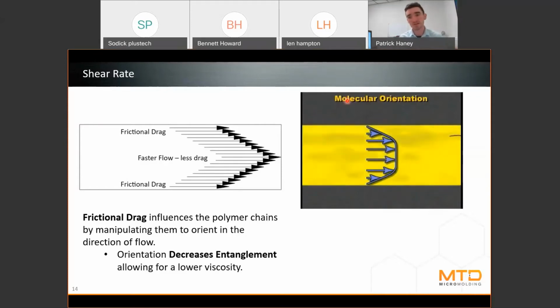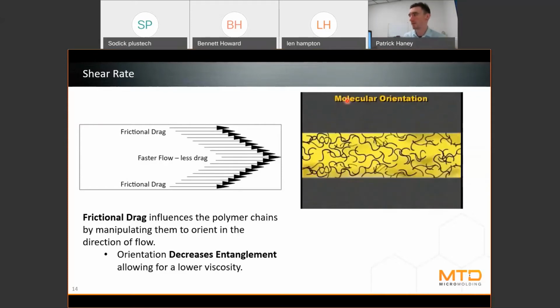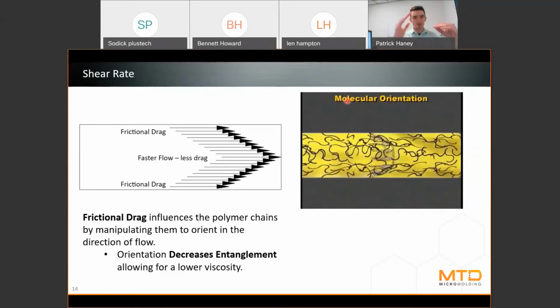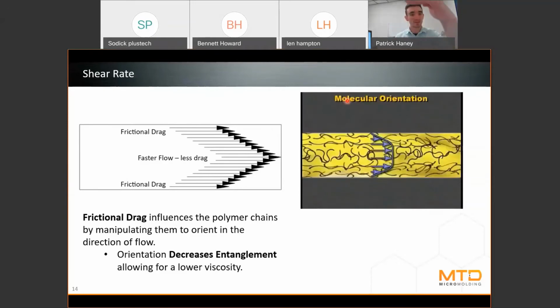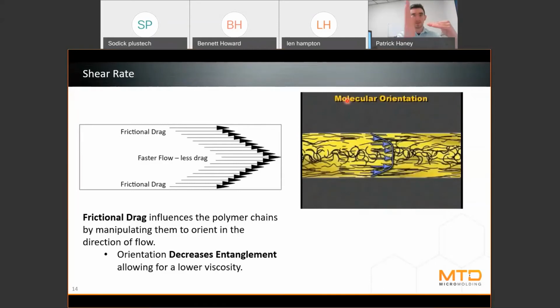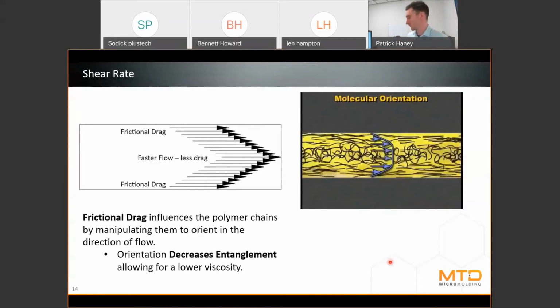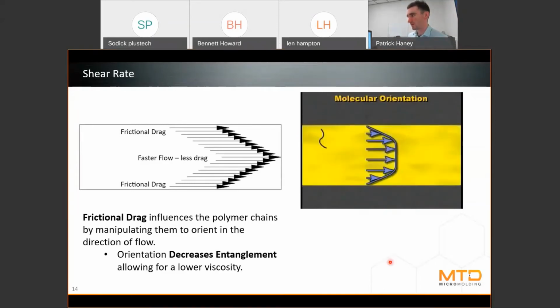Therefore, their velocities can go faster. Okay, so this differential in velocities from the center of the flow channel to the outsides of the flow channel. If you have, like in this example, a polymer chain that is perpendicular to the mold walls and then influence faster velocities near the center of the flow channel versus the outside of the flow channel, they will all tend to orient in the direction of flow.